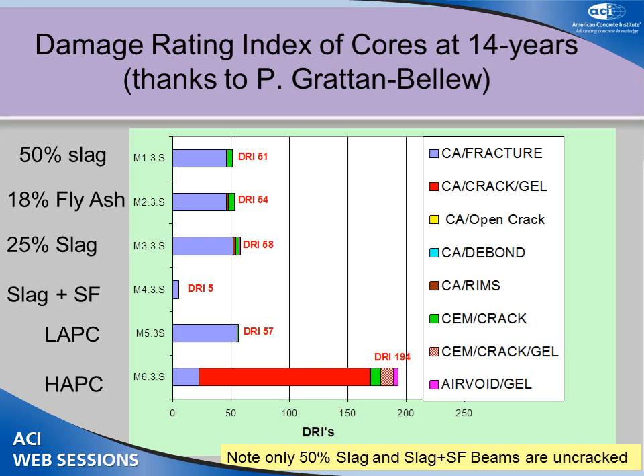You take a polished section and you look at crack interfaces. You look at cracks in the aggregate, cracks in the paste. You look at if there's gel present, those sorts of things. There are indicators, as shown by the colored chart on the right, and you add those up and you end up with a number. And the one, again, that has the lowest number is the ternary mix. There's almost no evidence of any damage.